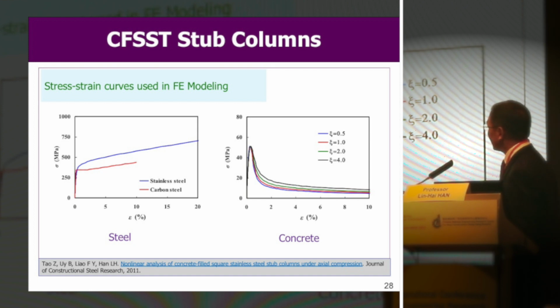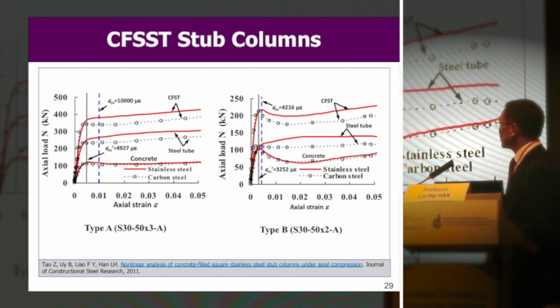You can see the stainless steel tube, the stress-strain relations, carbon steel. This austenitic steel properties. For the confined concrete, under different confinement factors, you can see concrete curves go like that. So this numerical analysis is to check the contribution of the outer steel tube and the inside concrete. You can see the contributions of the stainless steel tube, the hardening effects.